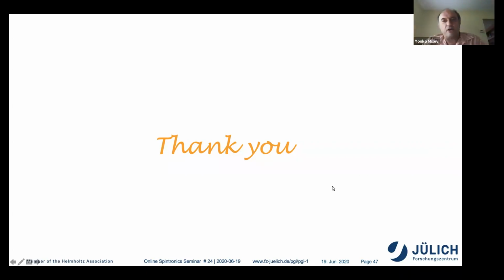Hi, Professor Blügel. Great talk. I have a question that touches on the spin reorientation transition. Just like you mentioned, responding to the previous question, magnetic anisotropy is a very subtle thing, and you know this better than most of us. So when you showed that plot where, depending on the thickness of the cobalt layer, things go down, and then there is a spin reorientation. Typically, since the Dirac factor hardly depends on these small thicknesses, it will be almost one in one direction, zero in the other. So traditionally, one speaks of surface magnetic anisotropy. Is it so that somehow it was included in your considerations, but you never mentioned it? Because that's usually what people think about when there is thickness dependence of that kind.